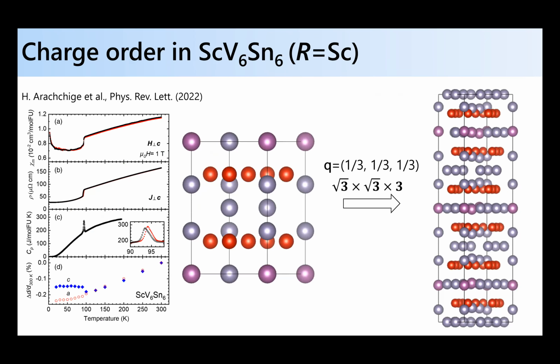Okay. But there's some work where, instead of yttrium, David Mandrus's group put in scandium, which is a much smaller ion than yttrium, in the lattice. When they did that and looked at the magnetization, resistivity and heat capacity, a phase transition appeared around 100 Kelvin. The superstructure that formed went from the parent 166 structure to a root 3 by root 3 by 3 enlargement, and the Q vector ascribed to this is (1/3, 1/3, 1/3).